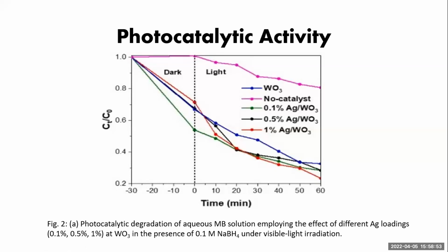Okay, sir. So the catalysts with various loading concentrations have higher photocatalytic activity, with 1% AgWO3 being the highest. After 60 minutes, we found the reaction rate constant using 0.1% AgWO3 to be 0.01366 per minute, for 0.5% AgWO3 we found 0.0141 per minute, and for 1% AgWO3 we found 0.01637 per minute.